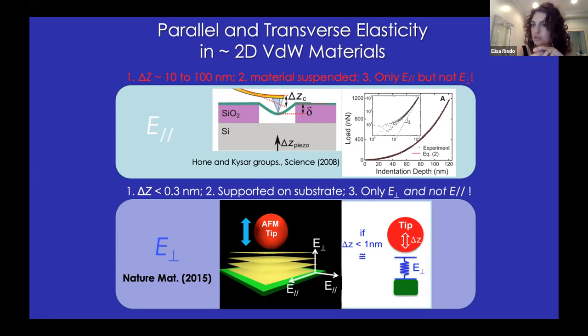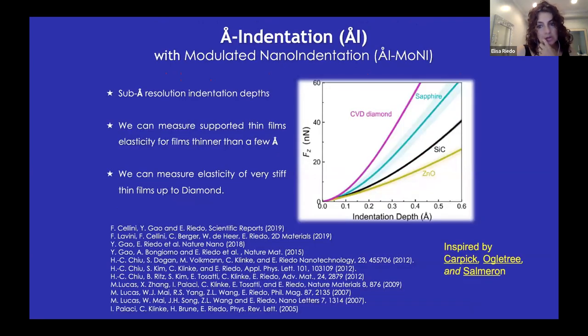Otherwise, you don't measure anymore the interlayer elasticity, but you measure a coupling with, for example, the substrate elasticity. So ideally, your indentation needs to be of the order of the Angstrom. So then you are in a very different regime and you need a different type of methodology. So because of this, we have developed what we called Angstrom indentation, just to maintain the tradition of micro indentation, nano indentation. Now we are into the Angstrom indentation regime, always using atomic force microscopes.